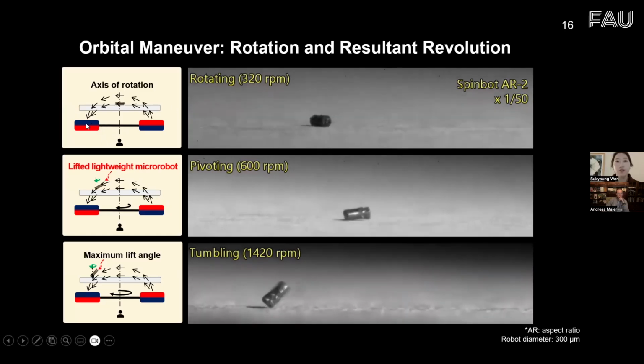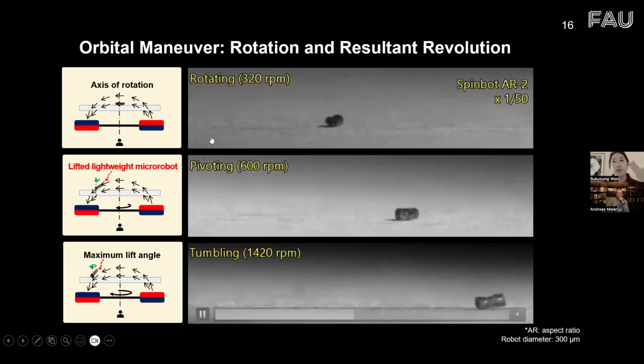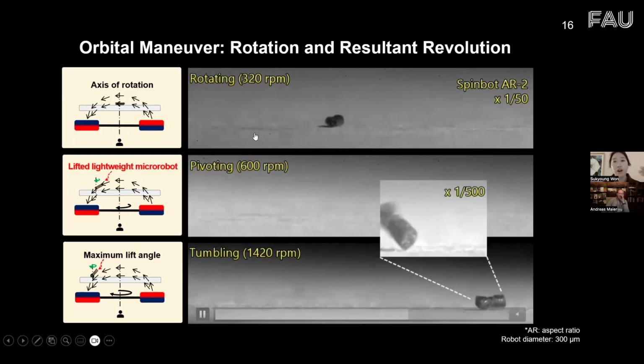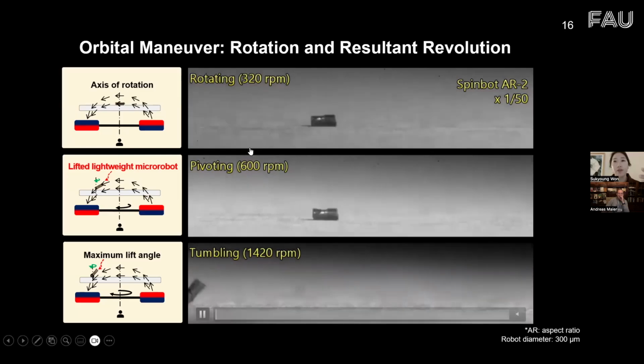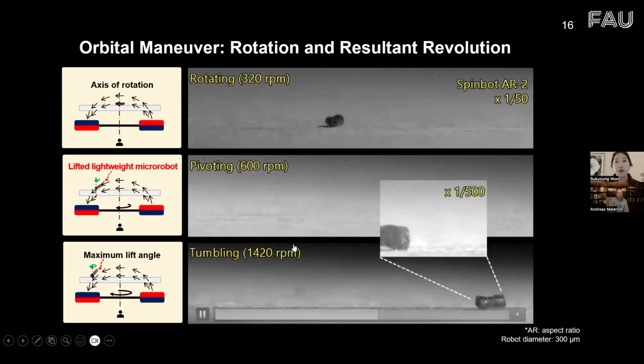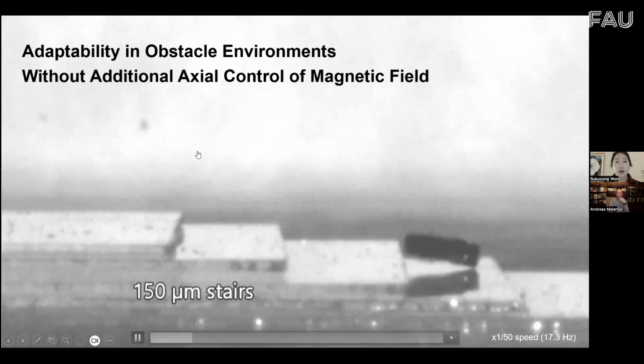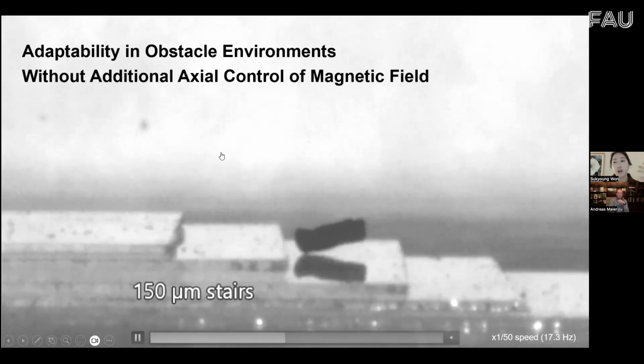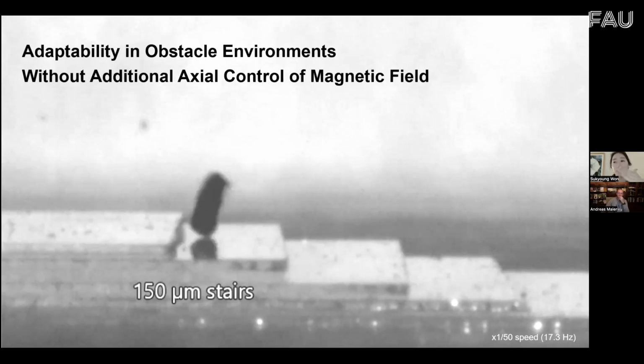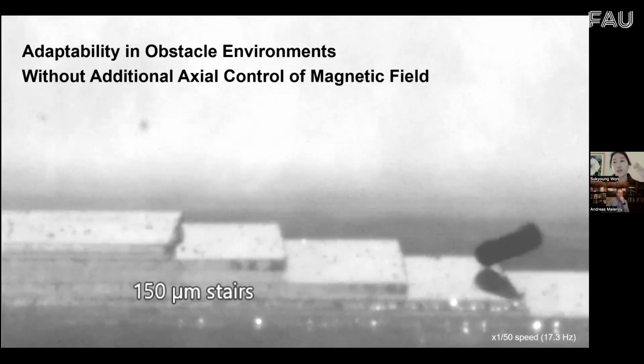When the two permanent magnets rotate underneath the microrobots, the robots follow the direction of the rotating magnetic field. So we can control the three multimodal actuations of rotating, pivoting, and tumbling depending on the magnetic frequency of the rotating magnetic field. Particularly at a high frequency of the magnetic field, the robots can show tumbling motions with a jump behavior, allowing them rapid actuation and also adaptability in the obstacle environment, even though we did not have additional control of the axis of the magnetic field.